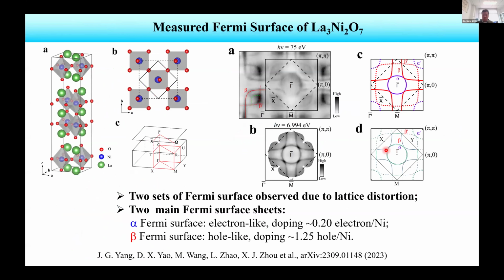Then we got a sample from Professor Wang's group, and we performed ARPES. We performed ARPES at the synchrotron-based system, Shanghai Synchrotron Radiation Facility, and by using a photon energy of 75 eV, we can map the larger momentum space.